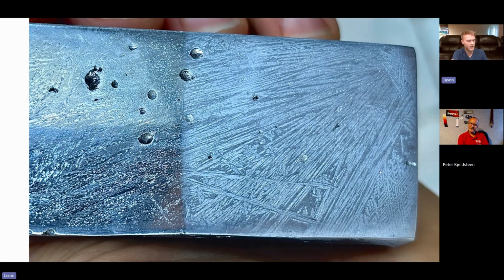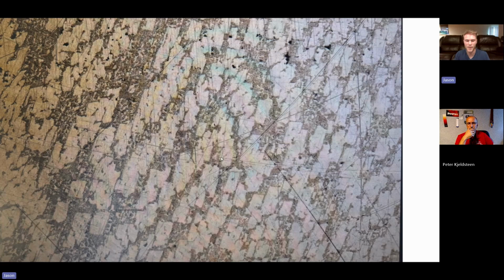What had me, I'm actually going to, just because we're talking about it, bear with me for a minute. You'll have to excuse the polishing job because I'm doing this all by hand. I don't have a polishing wheel at home. But this is that Widmanstätten-like pattern that we saw. You can see that each of those regions is almost like its own crystal. This one is its own crystal. Here's its own crystal. And then we see the eutectic in between, right? And this eutectic is pretty big, just the size of the alpha and theta regions, relative to something you would expect in more traditionally cooled materials.